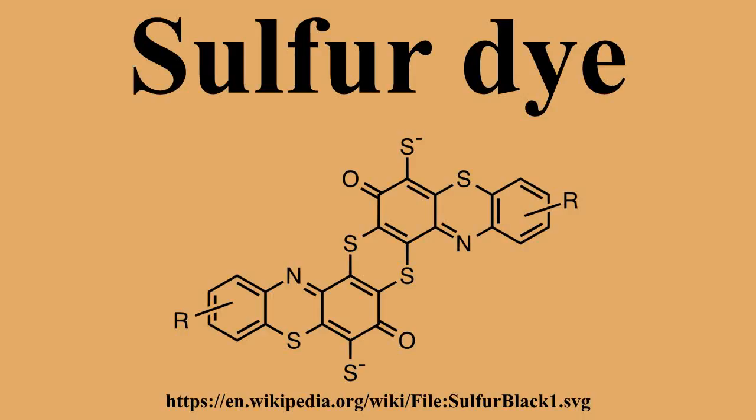After the fabric is removed from the dye solution, it is allowed to stand in air, whereupon the dye is regenerated by oxidation. The regenerated parent dye is insoluble in water. Oxidation can also be effected, in place of air, by hydrogen peroxide or sodium bromate in a mildly acidic solution. The low water solubility is the basis of the good wash-fastness of these dyed fabrics.